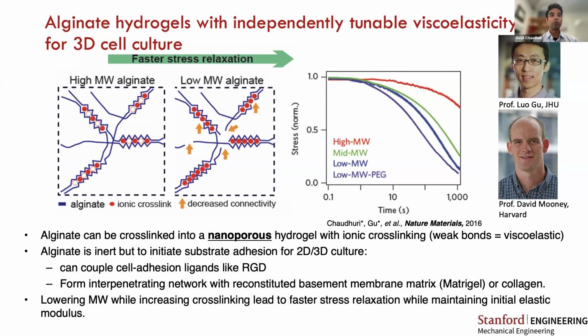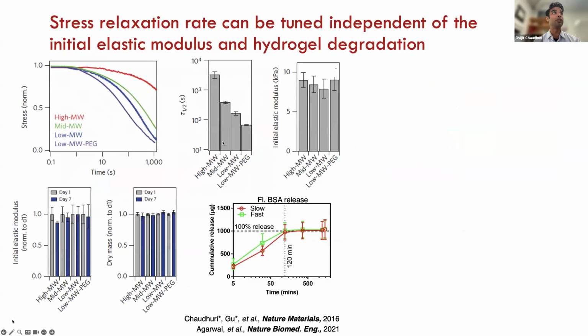Okay, so the idea we came up with was that if we altered the molecular architecture of these alginate gels, and in particular, varied the molecular weight while varying the ionic cross-linking density, we hypothesized that we could independently tune the viscoelastic properties. And indeed, that's what we found we could do.